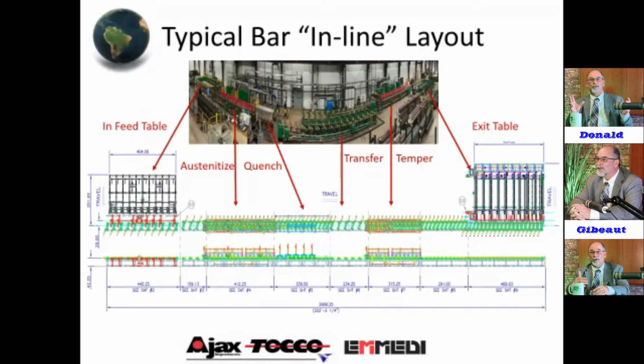And you go from your in-feed system, which is typically an incline table. We have paddle transfers that bring it over, or rotary transfers, and put it on a set of individually driven conveyor rolls. And we bring it together, and we butt it together right before it goes into the austenitizer. And then the austenitizer heating section here heats it up to that 1600 to 1850 Fahrenheit.